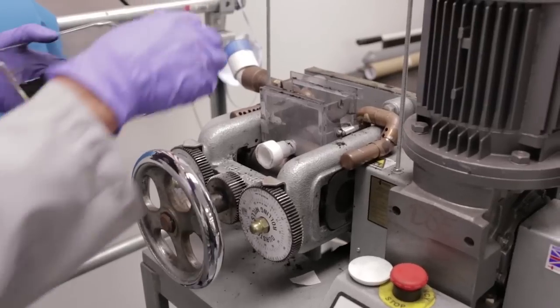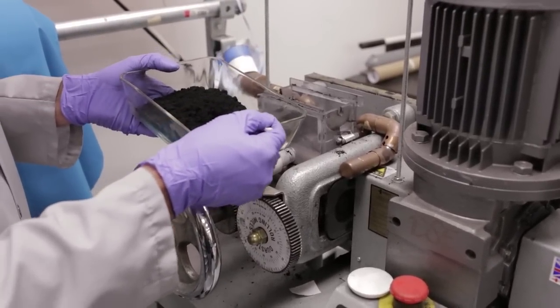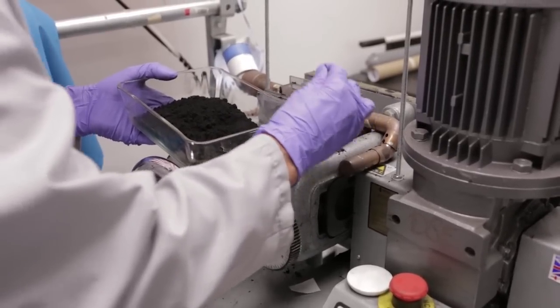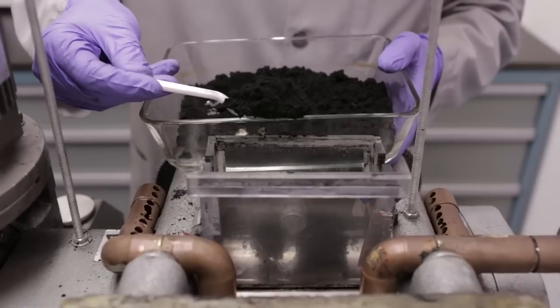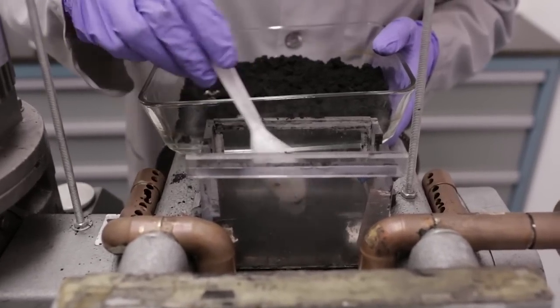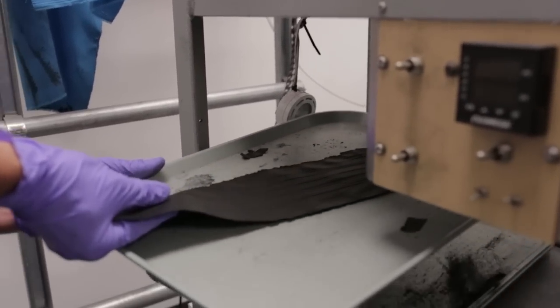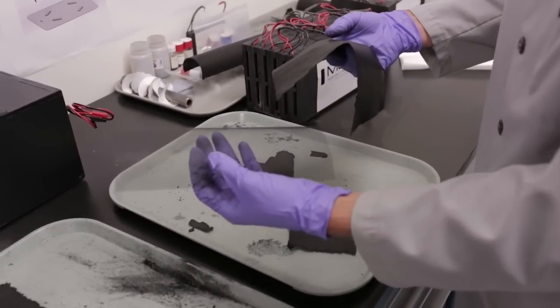This is our cathode production machine. I'll take our cathode mix that we just finished blending up over there and I'll add it to our machine where we have some fixed width rollers, which will actually take the cathode mix and it actually rolls it out into a sheet of pressed carbon and catalyst mix. Once that catalyst mix is rolled out into a nice sheet, I'll take it and I'll lay it on top of a nice nickel screen that we use as the current collector for the battery. It gets then rolled itself again, and the carbon gets laminated onto the nickel screen.